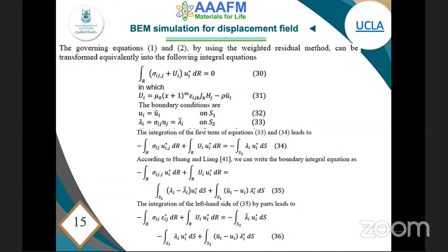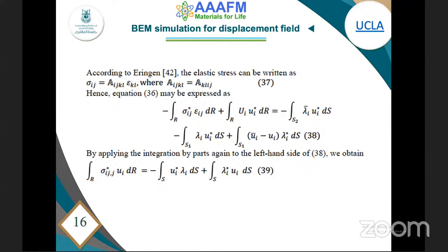The integration of the first term of equations 33 and 34 leads to, according to Huang and Liang, reference 41, we can write the boundary integral equations 35. The integration of the left hand side of 35 by parts leads to equation 36. According to Eringen, the elastic stress can be written as equation 37. Hence, equation 36 may be expressed as equation 38 by applying integration by parts. Again, applying it to the left hand side of 38, we obtain equation 39.